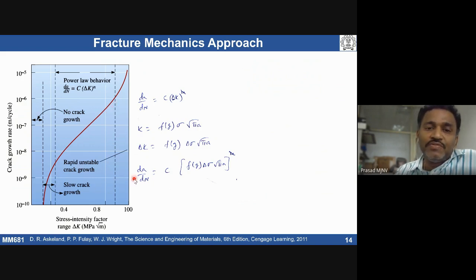So if I look here, initially there won't be any crack growth. After giving some threshold delta K, we start seeing the crack growth start taking place. So initially we have regime 1, regime 2, and regime 3, there are 3 regimes, as a function of how the crack growth rate changes as a function of stress intensity factor range. Typically a particular material can exhibit this kind of sigmoidal shape curve.